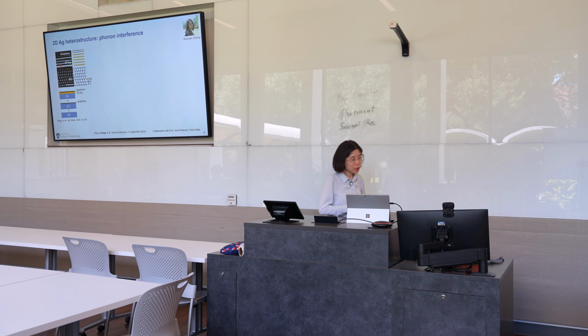We have strong evidence here. If you look at the cross-sectional TEM image, you can see this is silicon carbide. These are graphene, but in between, you have 2D atomic layers of silver. So now we have a very unique structure, 2D silver. It's different from the normal silver atomic structure. What's interesting about them?